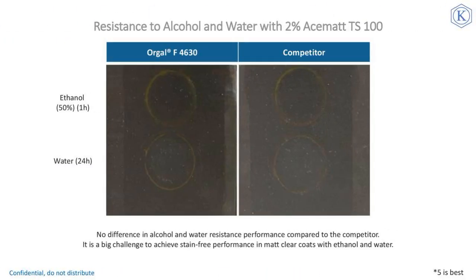Although it's not achieved, I would like to show you a picture. This is a demanding application on the market, and several customers are working on this topic, which is clear matte top coats on dark substrates, having ethanol and water resistance, 1 hour ethanol and 24 hours of water, without leaving any marks on the surface. As you see, the film clarity, the jetness of the black, the color strength of the black is really good with 4630, and we don't have any visible white stain after ethanol contact.